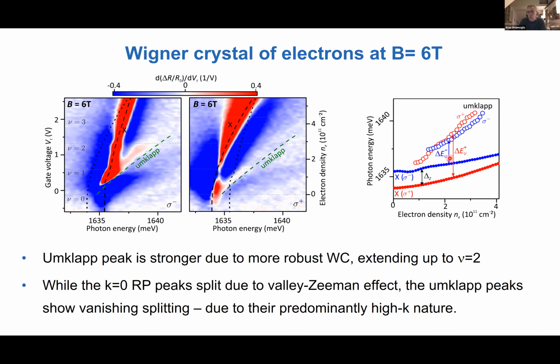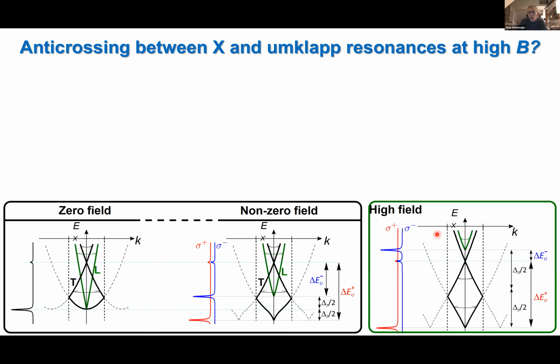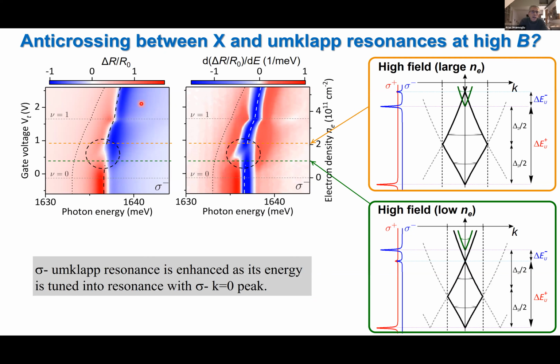And what that results in is that for one polarization, the sigma minus, the k=0 is closer in energy to the Umklapp peak, and that's why its strength is larger than the other one. Now, that gave us the idea that maybe we can make the Umklapp peak even stronger by tuning the energy of the sigma minus peak to higher energies using magnetic field and bring these into resonance. Indeed, the Umklapp energies are about 2 milli-electron volts, and the Valley-Zeeman effect with the g factor of 4.3 means that we can easily get our exciton into resonance. And this really worked nicely.